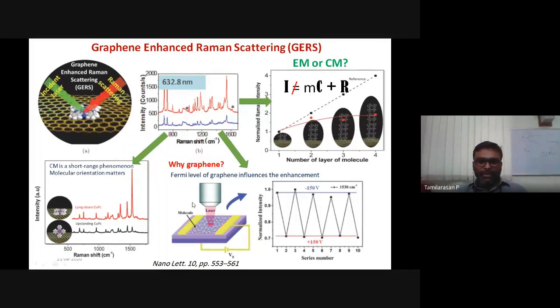And thirdly, they have also created a device, a graphene nano device, and by applying potential, they actually tuned its Fermi level. When they tuned the Fermi level, they got different intensities for different potentials. When they applied plus 150 volts, they got less intensity compared to minus 150 volts. Actually, what they have done is they have chosen two different potentials at the two sides of its Dirac point.